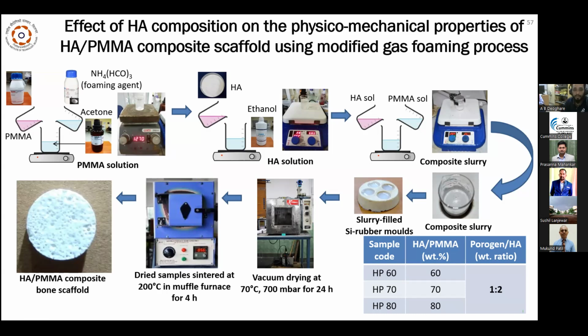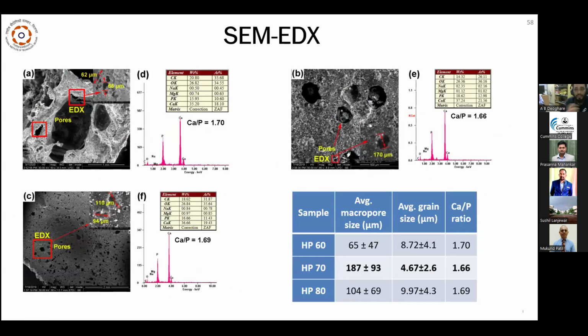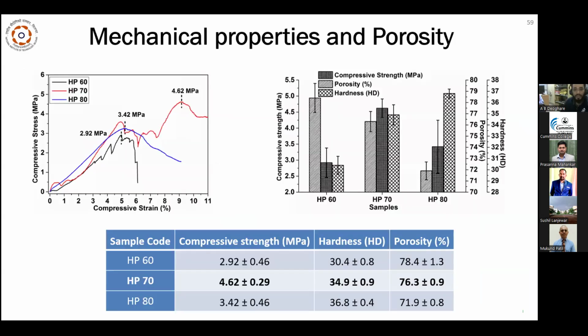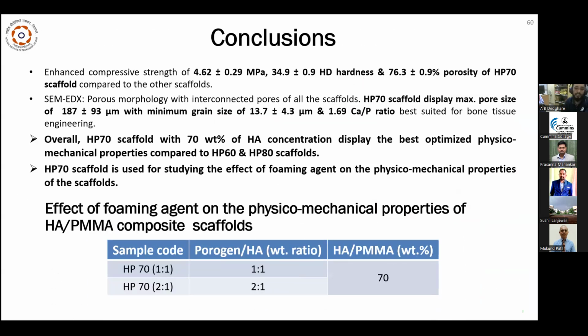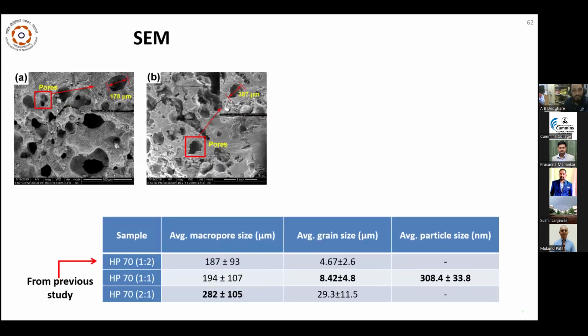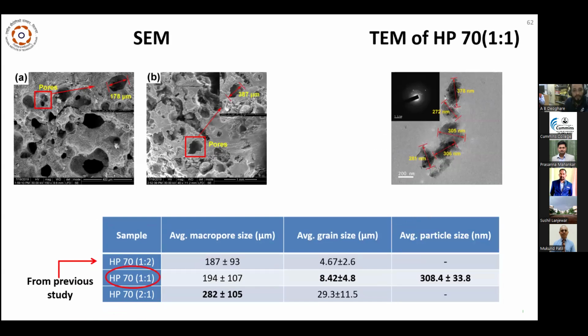After this, the hydroxyapatite PMMA composite scaffold is prepared, and from the same analysis, a porous structure is observed. From the mechanical testing, the compressive strength is observed to be higher for the sample with the hydroxyapatite to PMMA ratio of 70:30. From the above analysis, it is observed that the sample prepared at the 70:30 ratio gives better results. Results were also observed for the porogen to hydroxyapatite ratios of 1:1 and 2:1, and from the analysis almost similar results are observed. However, at the hydroxyapatite to porogen ratio of 1:1, it shows the better result.